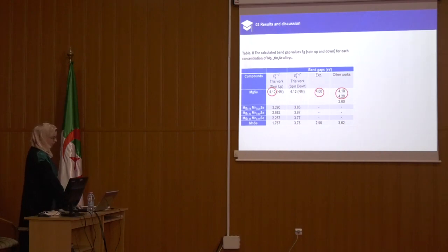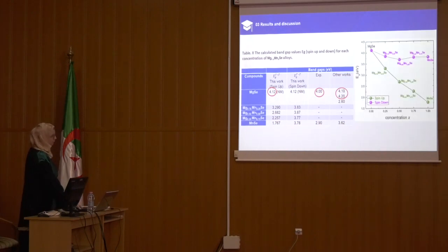In the figure, we present the band gap values in the spin up and down direction as a function of manganese concentration. In the spin up case, the energy gap value decreases with increasing concentration in our compound, whereas in the spin down case, the energy gap stays roughly the same, around 3.8.